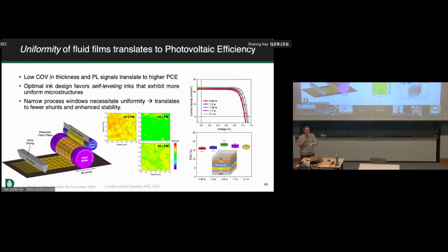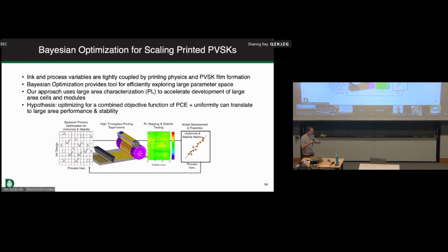So if you went out and bought a commercial silicon solar panel right now, you would get something about 20 to 22%, depending on how much money you spend. The perovskites that we print in our lab are about 18 to 20%, with champion efficiencies on the order of 21 now. But how do you go further? If you're going to go from the lab scale to something that's much larger, right? Square meters, you have to think about accelerating our development from the small scale to something that's larger and more complex. And the tool that we've been using in my group that Masha and Yana have been leading is essentially an applied machine learning technique.